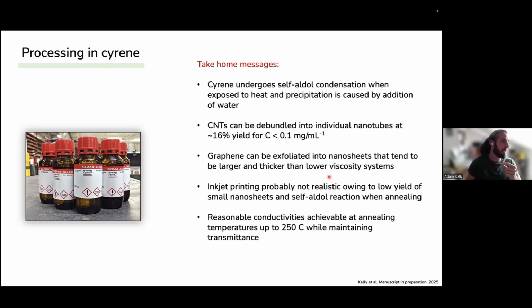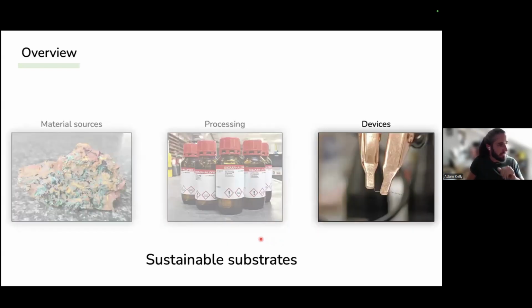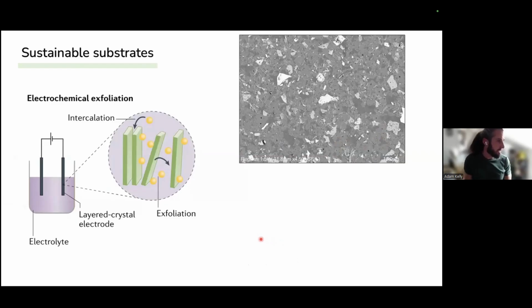And then when you go to anneal away the material, we have this reaction again, which creates these nice crystals, but not good for conductivity. But we can also produce reasonable conductivities for annealing temperatures up to 250 degrees while maintaining transmittance. So the last, very quickly, thing I want to show you is devices. So we had a